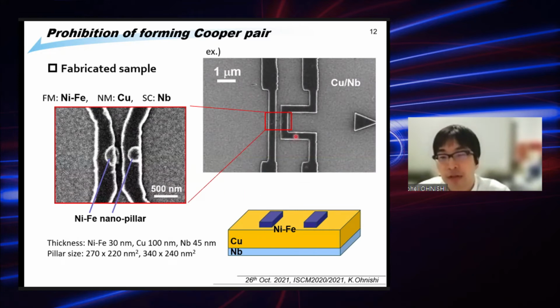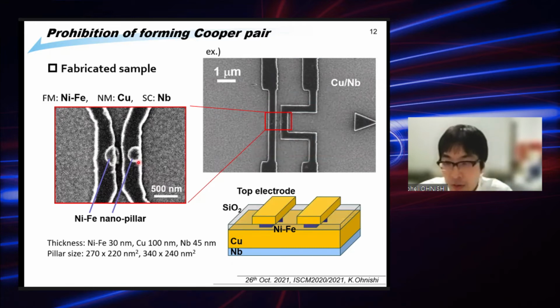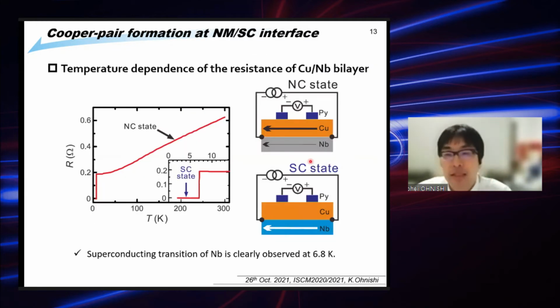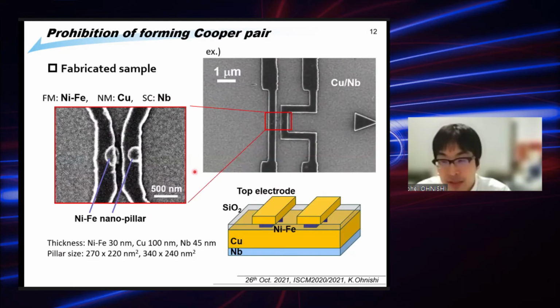This is the actual fabricated device. Over this large area there is the copper-niobium bilayer. On this large bilayer, we fabricate two small permalloy dots. In this case, we use permalloy, nickel iron. After fabricating these two dots, we fabricate the top electrodes to reach these two dots.